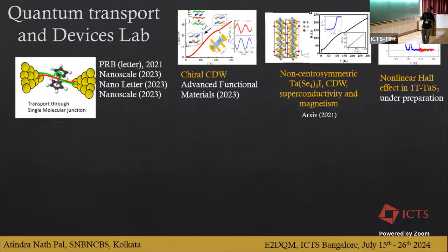And then we are also working on several quantum materials, looking at the chiral charge density wave materials, like planar Hall effect and different transport behaviors, where you observe unusual planar Hall effect, like change of sign in this material. Then we are also looking at quasi one-dimensional CDW material, where we also observe superconductivity and some weak ferromagnetism. And recently we are working on 1T-TaS2, where we are observing some kind of nonlinear Hall effect.